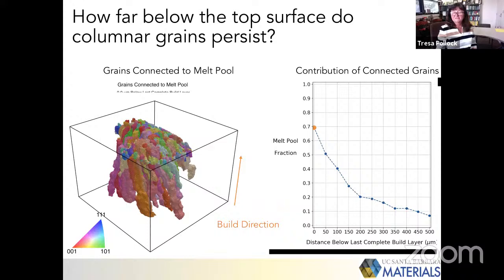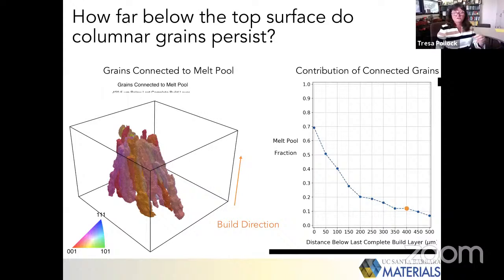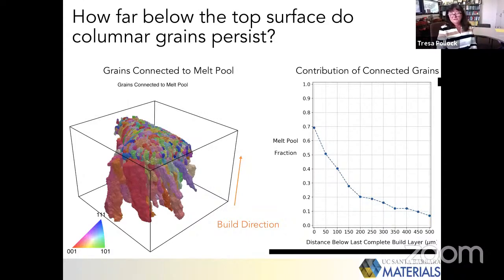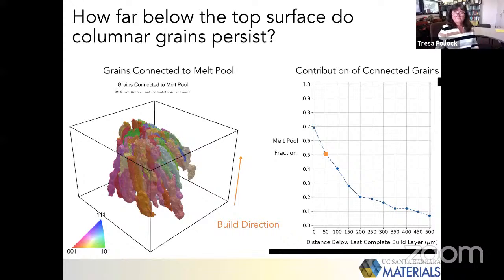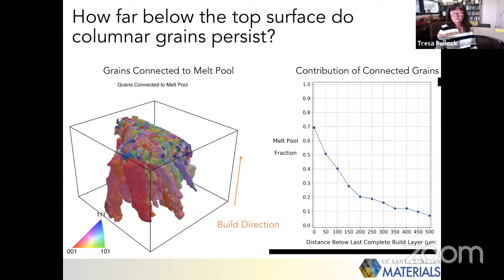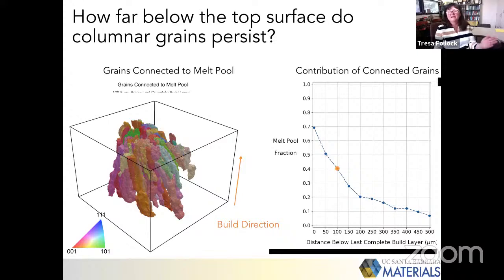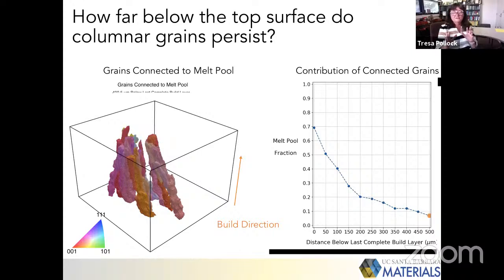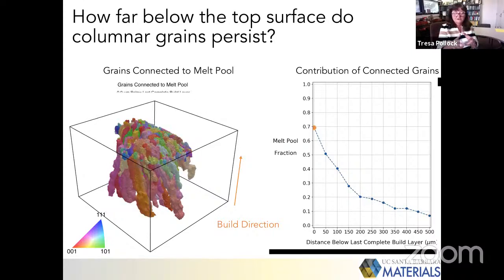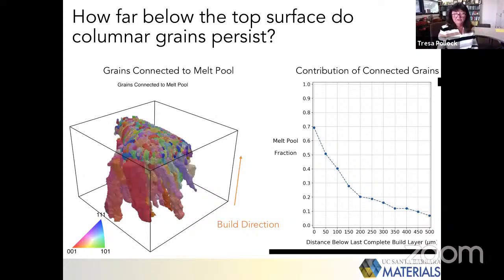And so one can basically track the development of these grains and understand the degree to which we have independent nucleation versus grains that persist from the layers below. And so what you can see is that in this top layer, there are actually many grains that extend back 10 layers below the melt surface. And so this is one of the things that has to be included in the modeling. One cannot necessarily just on the fly change the structure because there's all this history from the layers below you.